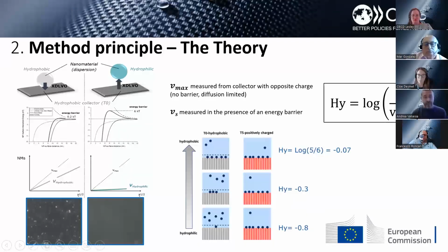What happens if we don't have any energy barrier? This happens, for example, when I have a collector characterized by an opposite charge than the one present on the particle. If I have an opposite charge, there is no energy barrier, so the particles are free to bind on the collector. This is how we measure the maximum velocity, the maximum binding rate of particles on the collector. This is our normalization factor, let's say.